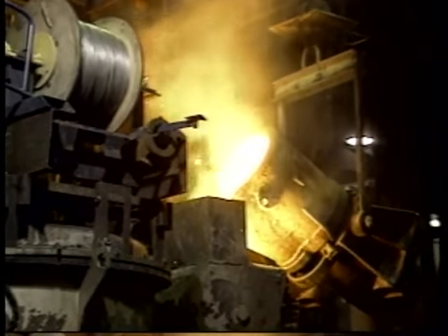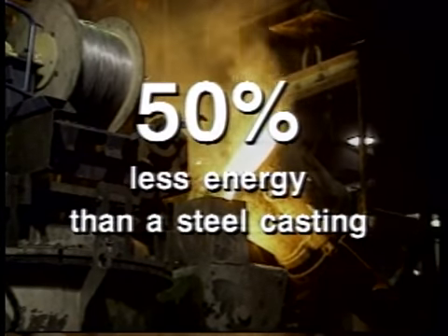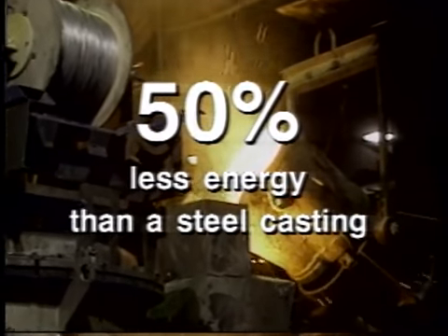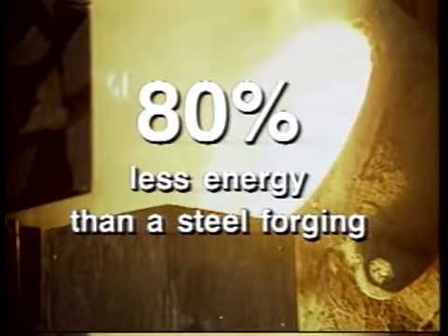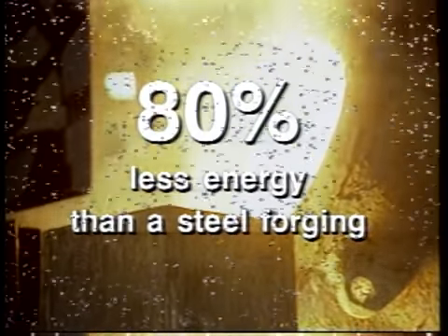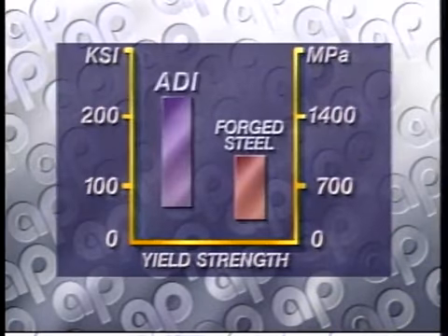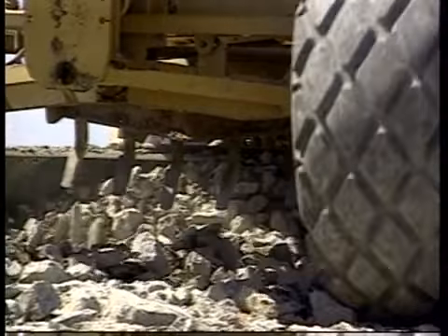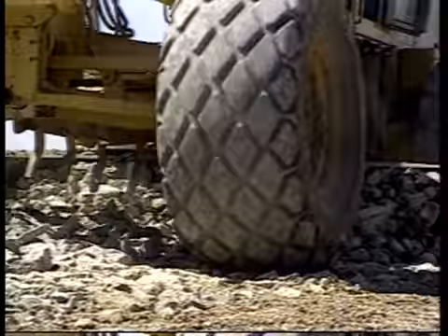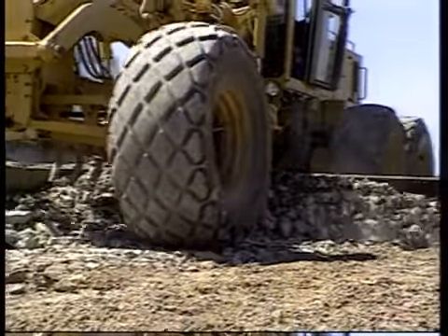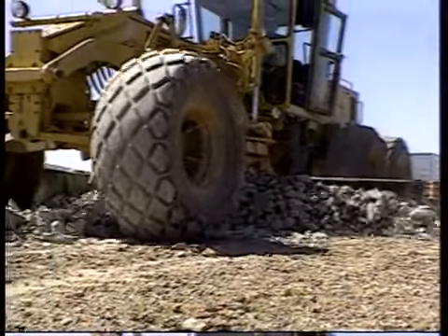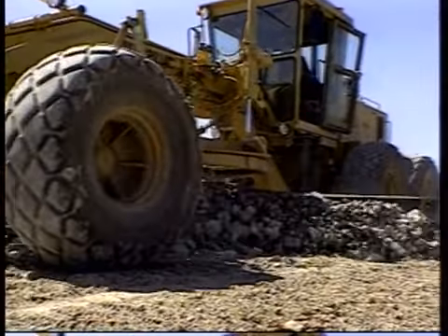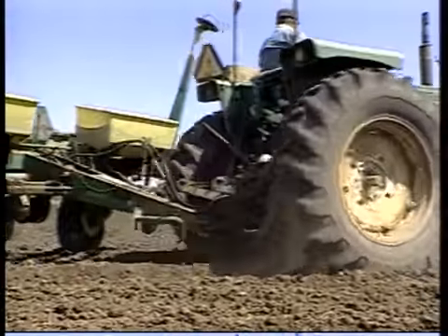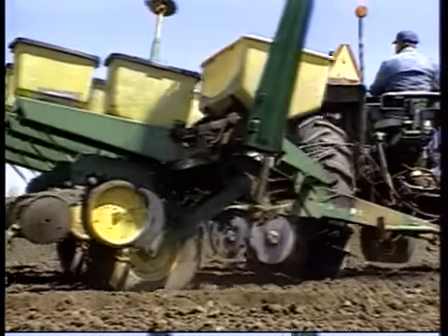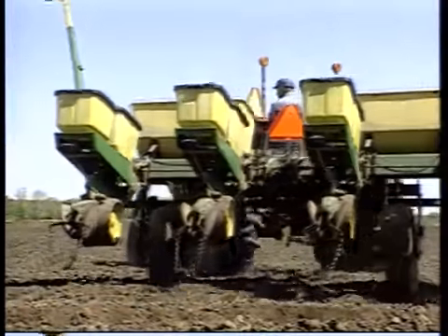An ADI component uses 50% less energy per unit of weight to produce than a steel casting, and 80% less energy than a steel forging. And ADI is stronger than microalloyed forged steel with comparable fracture toughness. Because of ADI's unique ausferrite matrix, for a given level of hardness, it will exhibit significantly better wear resistance than conventionally hardened steel. ADI has successfully replaced manganese steel and carburized steel in many wear applications.